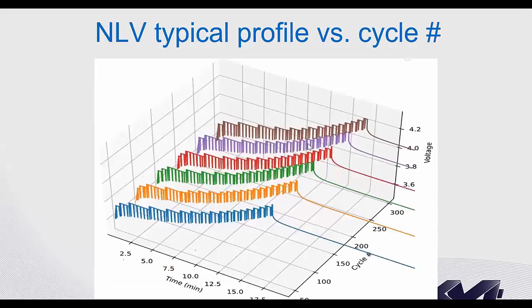So the voltage profile here shows the charging of a battery at different cycles. So this charge is in 15 minutes. We go from 0 to 100% in 15 minutes. This is the first time I think you can see charging a battery in less than 30 minutes or 20 minutes. This is in 15 minutes, and we were able to apply NLV for more than 300 cycles. And you can see here that the charge profile is almost the same, whatever the number of cycles we have run between 0 to 300 cycles.